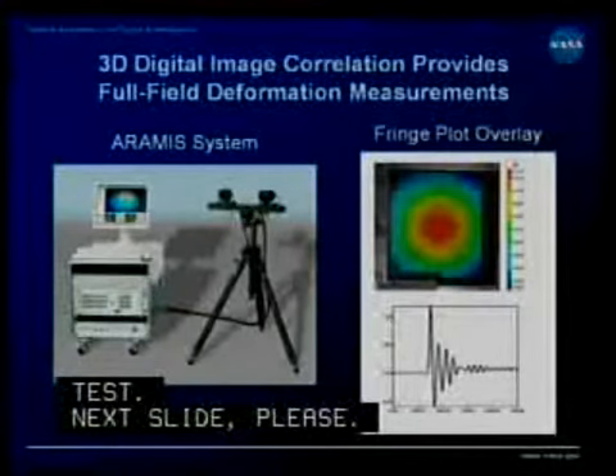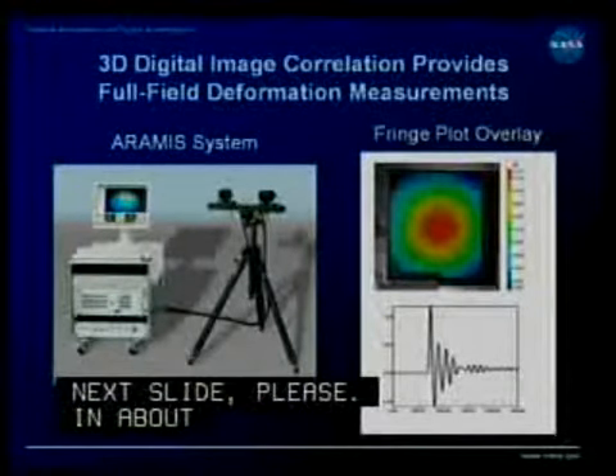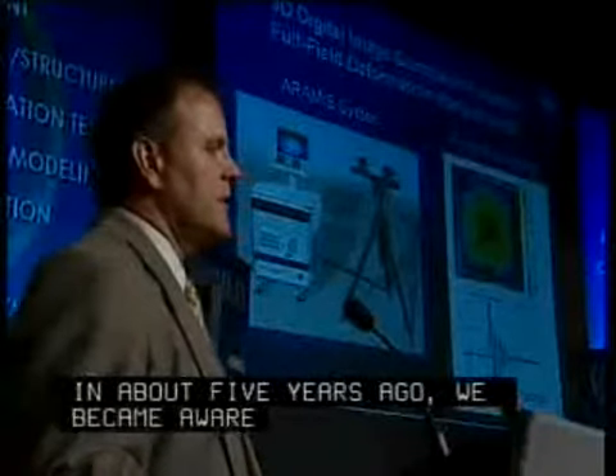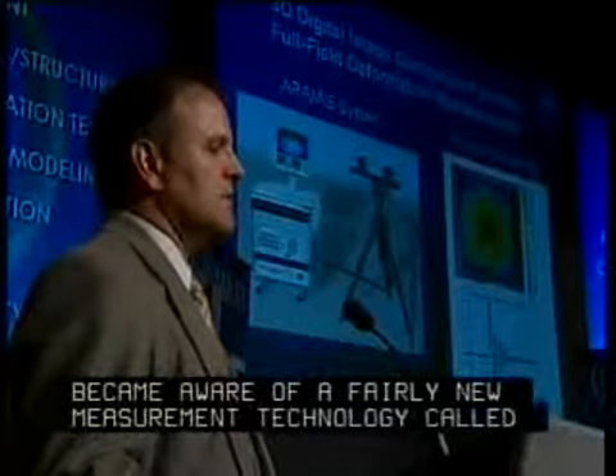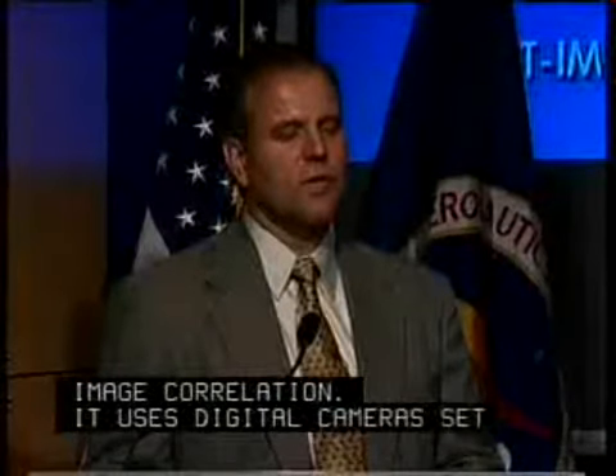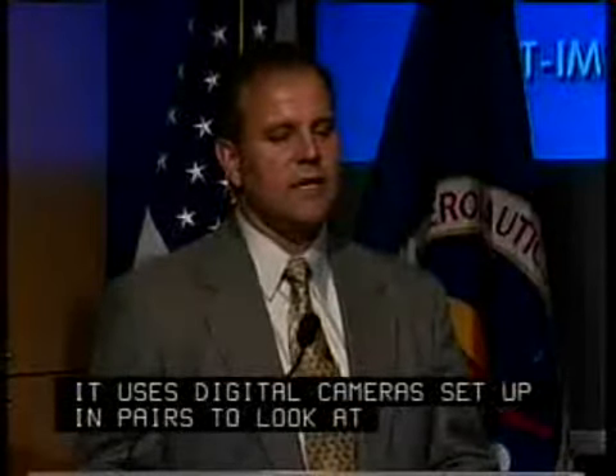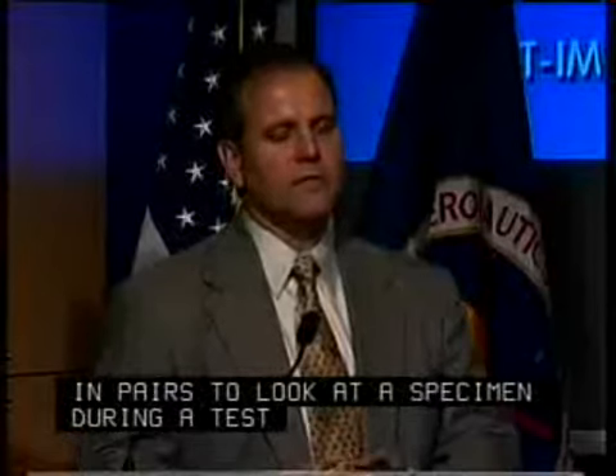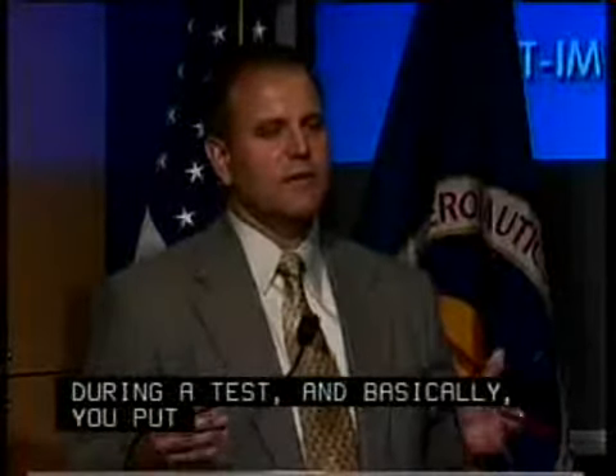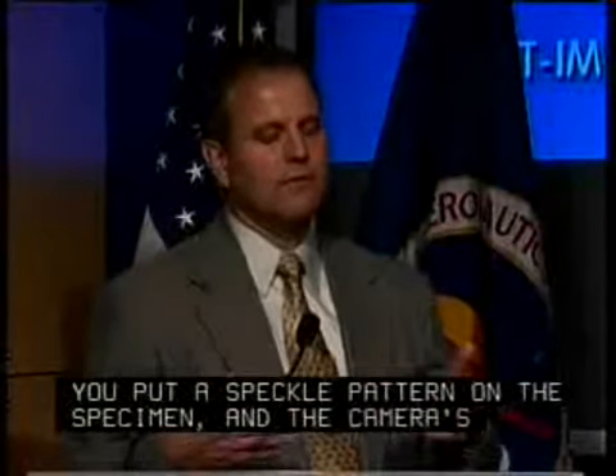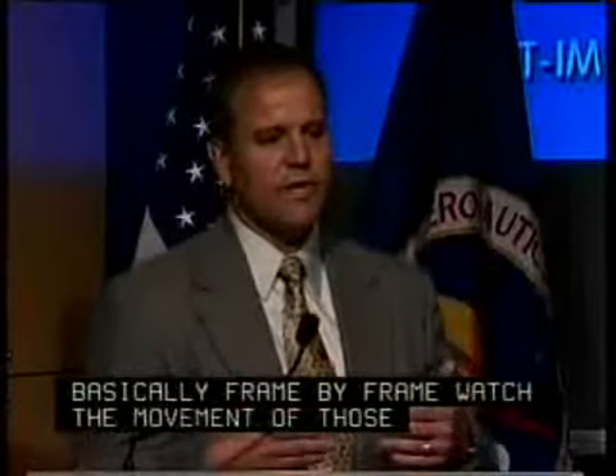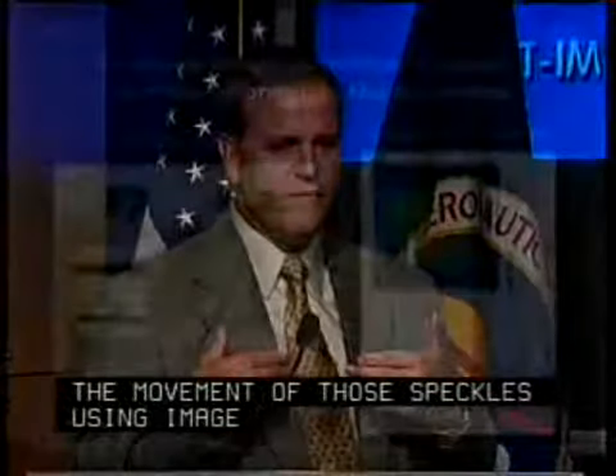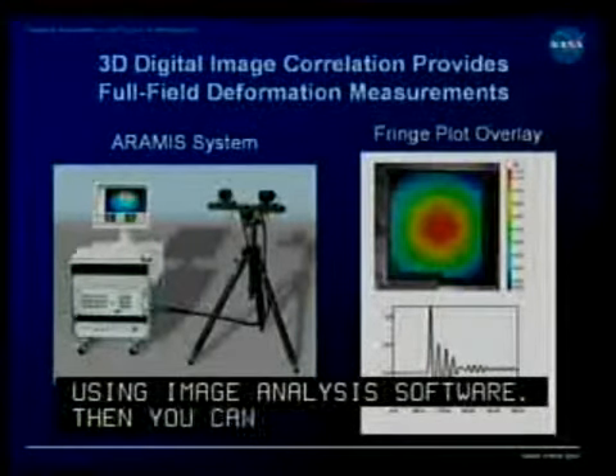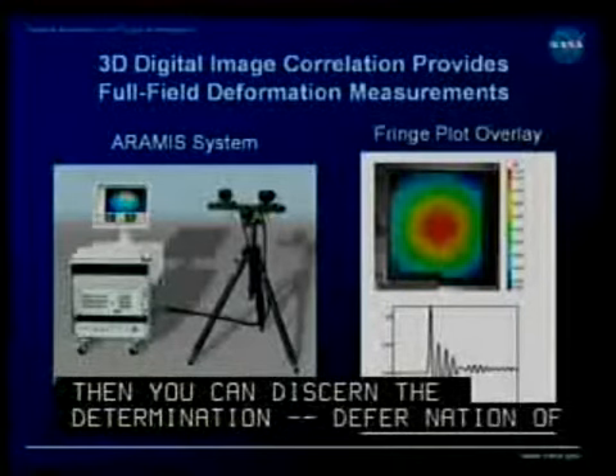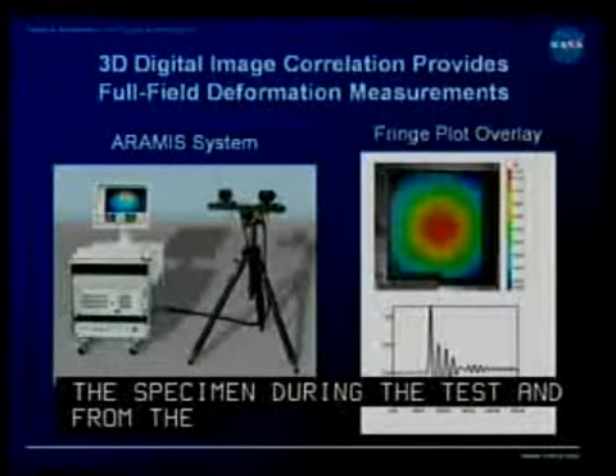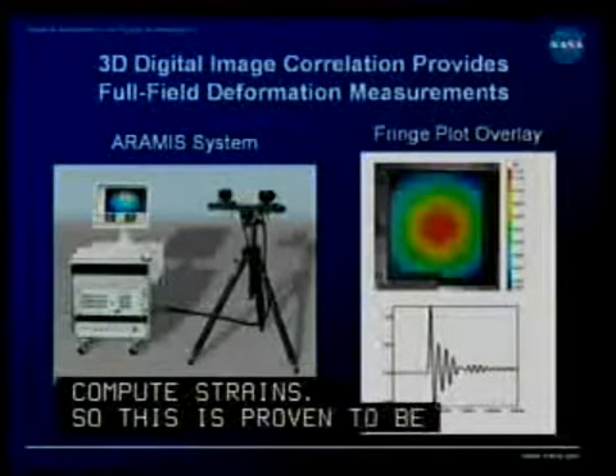About 5 years ago, we became aware of a fairly new measurement technology called image correlation. It uses digital cameras set up in pairs to look at a specimen during a test. You put a speckle pattern on the specimen, and the cameras, frame by frame, watch the movement of those speckles. Using image analysis software, you can discern the deformation of the specimen during the test, and from the deformations you can compute strains.